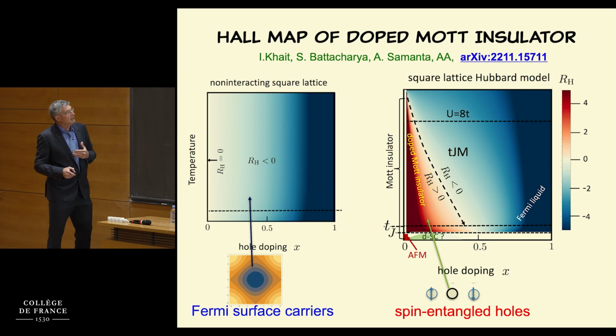And you can understand all the metallic behavior in such a non-interacting model with the Fermi surface. On the other hand, the TJ model, which close to half filling really is described by these projected holes, has a completely different behavior of the Hall coefficient. First of all, the sign gets reversed already at quite high doping. Okay, so the effect of the Mott phase, this is a Mott insulator that doesn't allow the electrons to move, is quite deep into the phase diagram.